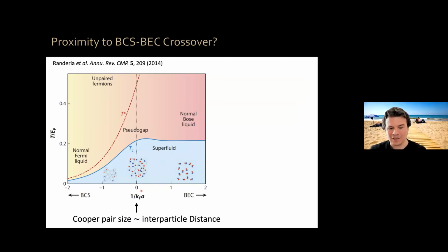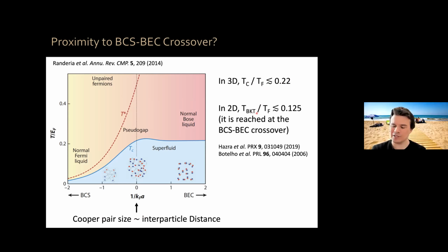And in this BCS to BEC crossover, the Cooper pair size is of the same order as the interparticle distance. In 3D, the critical temperature versus the Fermi temperature is bounded, at 0.22. In 2 dimensions, it is the BKT temperature over TF, which is bounded at 0.125, and it's reached at the BCS-BEC crossover.